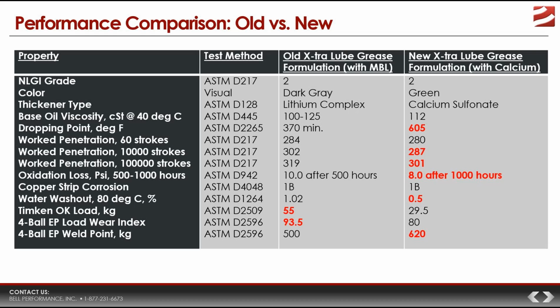They take a bearing housing and pack it with a given test grease, and warm everything up to a specific temperature so everything is standardized and controlled. Then they rotate the bearing at 600 RPM, so it's going around 10 times a second basically. At the same time, they're adding water at a controlled rate, 5 milliliters per second, and they do this for 1 hour. Then they stop the test, dry everything out, and put the bearing pack in an oven, about 170 degrees for about 16 hours, to help dry everything out.